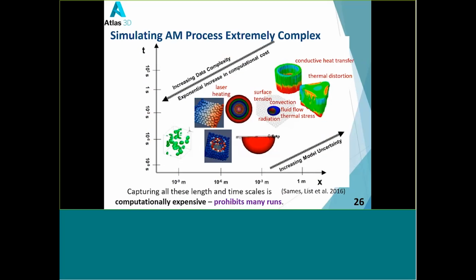The problem is that in order to do this high-fidelity modeling, it takes lots of hours, even if you use a supercomputer, and the simulation domain is very small. So we need to really rethink how we can model the whole process. This figure shows the AM model with different time scales and different length scales. It is computationally intensive to capture the physics at all the length scales and time scales. So we really want to think about what time scale and what length scale we want to simulate. And for optimization, for real applications, we need to simulate parts with size up to 1 meter.